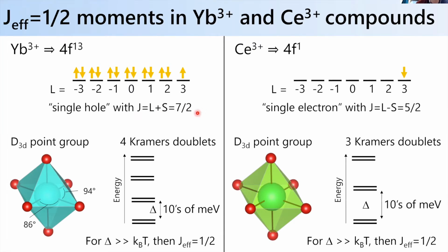Okay, so it's a Kramers ion, so you're always going to have a doublet, right? Unless you break time reversal symmetry. And once we lift this degeneracy, what you're left with is a ground state doublet, okay? And the splitting between this ground state doublet and the first excited state doublet for an insulator can often be on the order of tens of meV, depending on the details of the system.